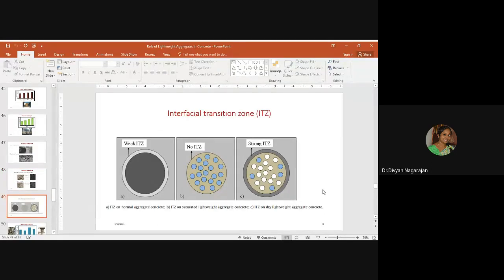Interfacial transition zone. Being porous aggregates, these aggregates have a strong interfacial transition zone. The interfacial transition zone has significant influence on the mechanical and durability properties of any hardened concrete. The quality of the interfacial transition zone depends on the type, density, surface structure, and moisture state of the aggregates. Therefore, the sintered fly ash aggregate, being porous in nature, has a good interfacial transition zone.